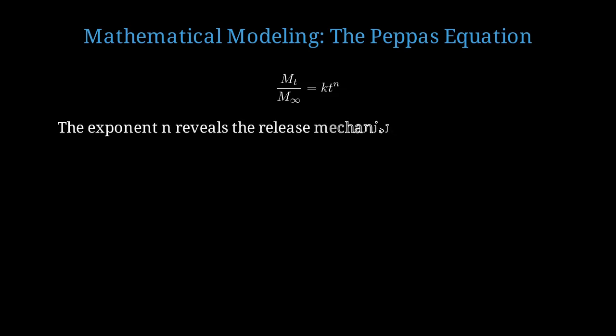The value of n is diagnostic. For spherical particles, n equals 0.43 indicates Fickian diffusion. If n equals 0.85, it's case 2 transport, meaning swelling-controlled release. Values between indicate anomalous transport, where multiple mechanisms operate.